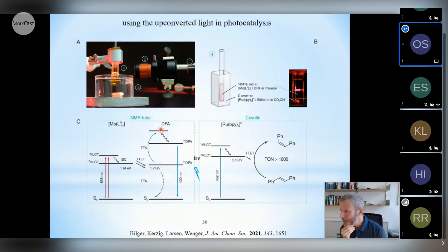They took a tube, an NMR tube, and they placed into this NMR tube the upconversion mixture. They had the molybdenum complex in there and the diphenylanthracene. They excited this with red light and they got out blue delayed fluorescence. And then they did a radiative energy transfer across a glass wall here. The blue light went out of the NMR tube into the cuvette where they had ruthenium tris-bipyridine, which would absorb the blue up-converted light, and only the blue up-converted light, not the red input light. Of course, ruthenium tris-bipyridine is transparent at 635.